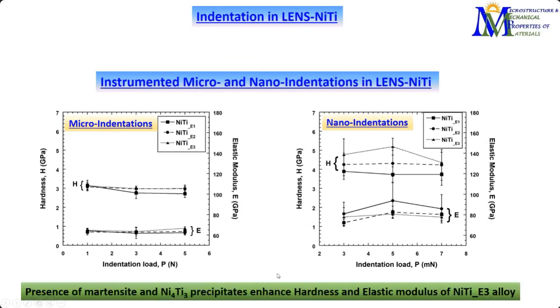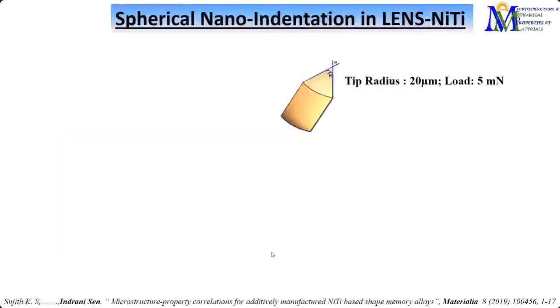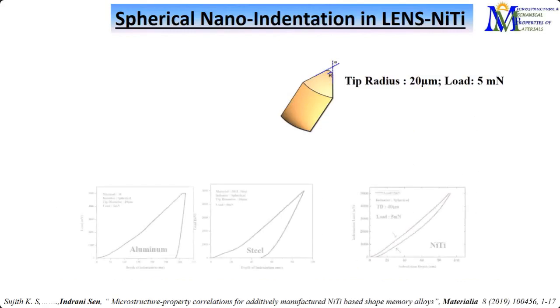Okay, so this is what we have seen: the presence of martensite and the precipitates enhance the hardness and elastic modulus of the alloy, which is produced with the highest energy density. So far people would have been happy that if we increase the energy density, we end up having lesser porosity and higher hardness. But that may not be the case, since we are talking about a pseudoelastic material, which is capable of recovering its shape.